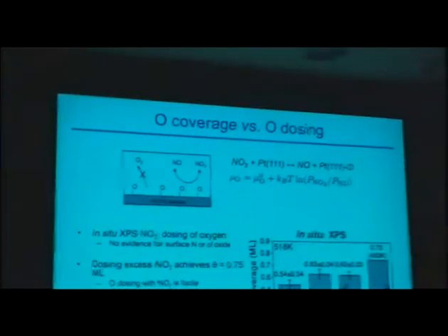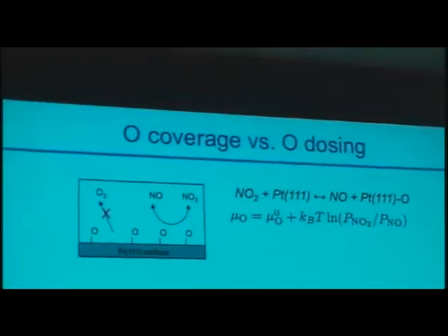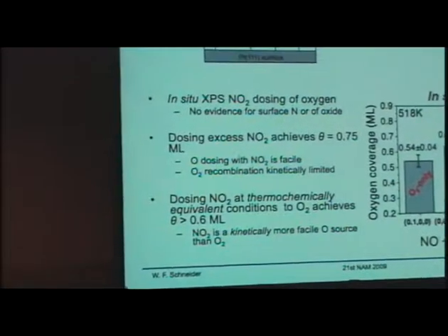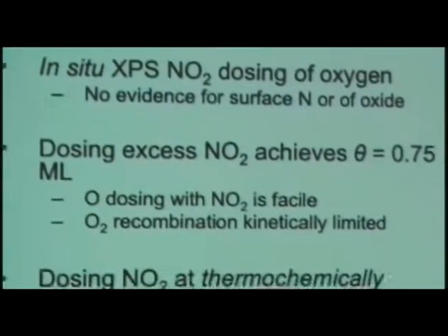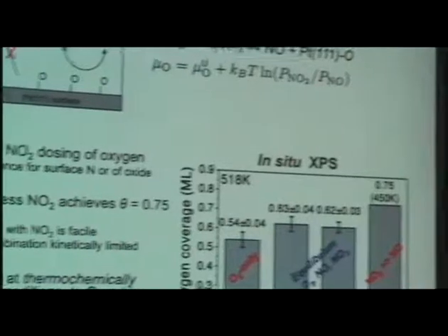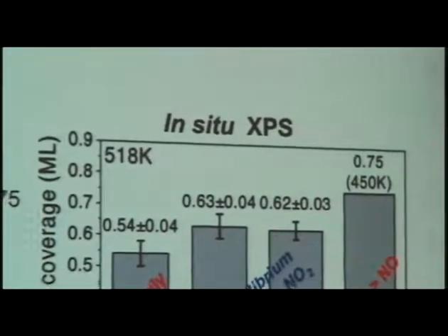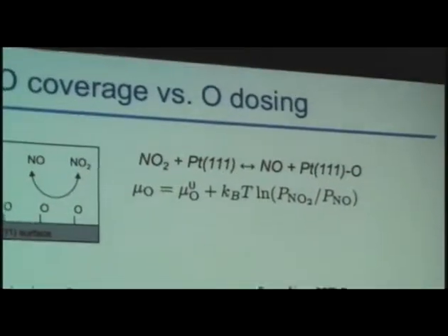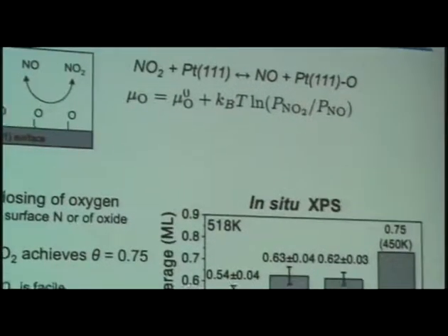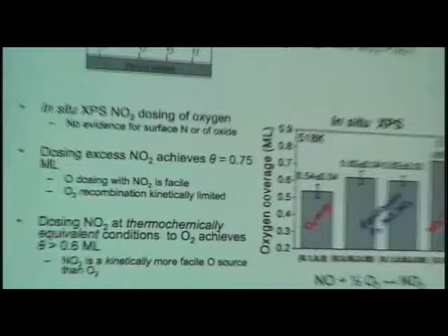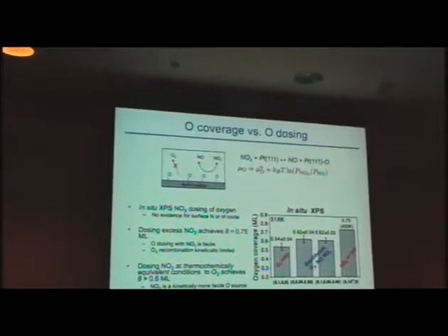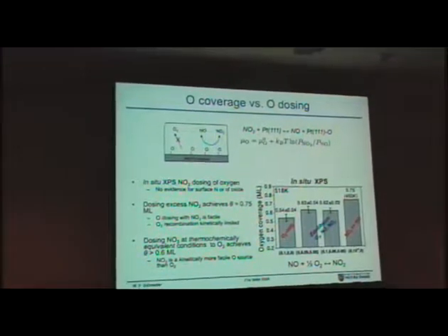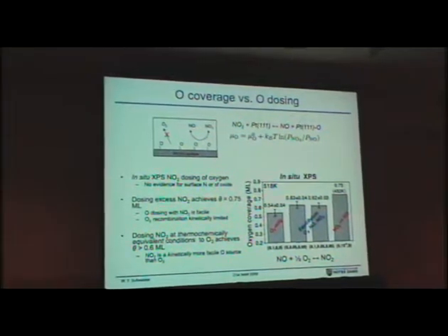will. This is consistent with experiments. Fabio Ribeiro and Andy Smelt and a number of other people did some experiments at a light source in California, as a matter of fact, looking at the relative rates of O2 dissociation and NO2 dissociation on a platinum surface. And what the results show is that indeed this NO2-NO reaction maintains its rate at higher coverages than the O2 dissociation. The O2 dissociation reaction basically shuts off once the oxygen coverage hits about half a monolayer, whereas the NO2-NO reaction remains fast at higher coverage. So that's a nice confirmation of what the DFT calculations showed.